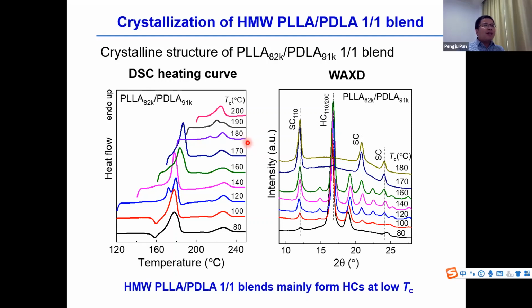When the crystallization temperature is lower than the melting temperature of homocrystal, we mainly observe the melting peak and the diffraction peak of homocrystal in the DSC heating curve and the WAXD pattern. When the crystallization temperature is higher than the melting point of homocrystal, homocrystal can't be formed, and we just see the melting peak and the diffraction peak of stereocomplex. The crystallinity of stereocomplex changed little with temperature in this wide temperature range. This means the high molecular weight PLLA and PDLA blend mainly forms the homocrystal in the crystallization temperature range of homocrystal.